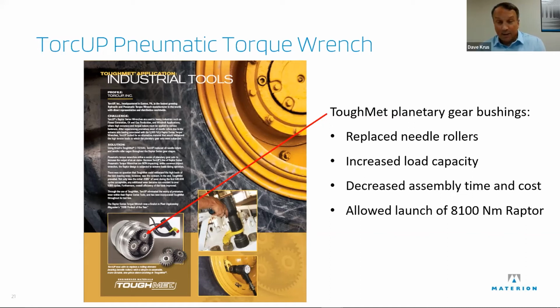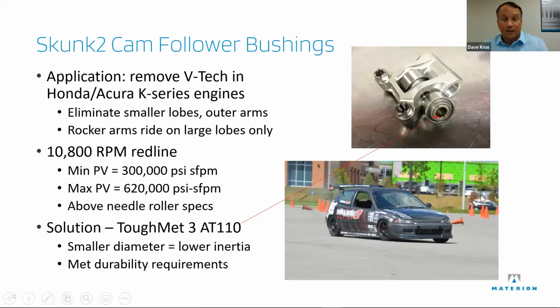But about that time, some people at Skunk 2, and this was published actually in Race Engine Technology, needed cam follower bearings, and they were having some problems. They take out the VTEC and just run a double rocker arm on the big lobe, right? And it generates a lot of power, but it also generates a lot of pressure on that follower roller. So when they couldn't find a needle roller that was specified for these high PVs, 620,000 PSI-surface feet per minute, it's high. And when they put in Tough Met, they were able to downsize the roller because it had a smaller area that gave them less inertia, and it met the durability requirements. Never had one fail.